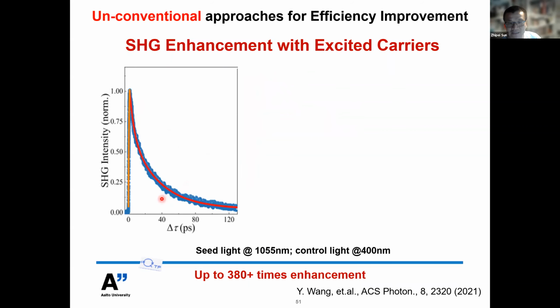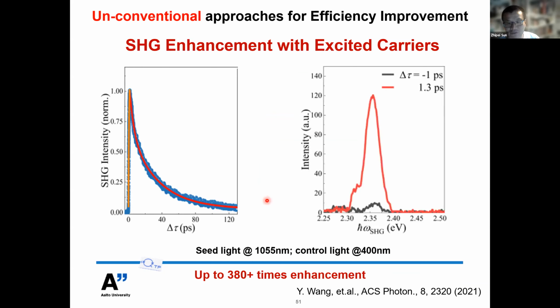Our results show that the second harmonic generation intensity increases significantly with the time delay. This indicates a very strong enhancement with the excited carriers created by the control light. This figure gives a little bit more information. The black curve shows the second harmonic generation without the control light, and with the control light, you can see the second harmonic generation increases significantly. We attribute the enhancement effect to the excited excitonic state created by the control light.